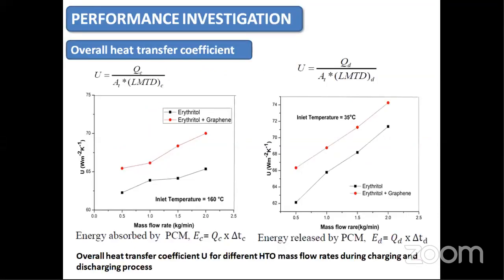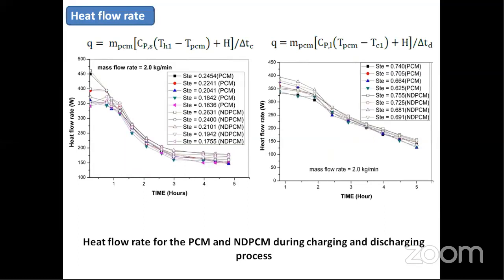Then the performance investigation we have done. The overall heat transfer coefficient increased 7% during the melting process and 6% during the solidification process. Then heat flow rate. At the beginning of the melting process, heat flow from heat transfer oil to phase change material increased by 3%, and for heat transfer oil to the nano dispersed phase change material it is 4%, for a 5 degree increase in inlet temperature. At the beginning of the solidification process, heat flow from phase change material to heat transfer oil increases by 4% and for nano dispersed PCM by 7%.